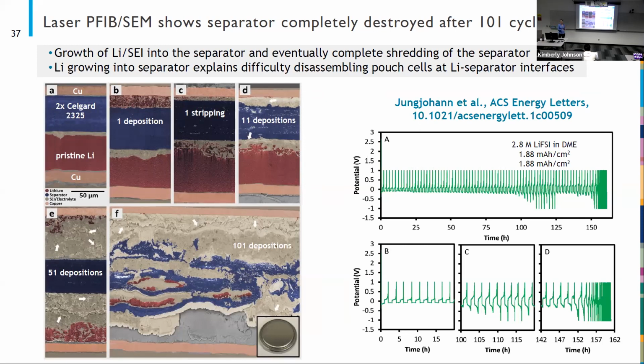And so in the first deposition, we can see we plate lithium onto the working electrode, we strip it from the counter electrode, we see lots of evidence of bulk lithium along with some SEI regions. And then we strip that away and there's a bunch of material left, right? We don't get it all back. Some of it turns to SEI and we can still see some bulk lithium there that must be disconnected or dead lithium. After 1 and 11 depositions, we actually start to see some evidence of junk forming in the separator that doesn't look like separator anymore, that we think is infiltrating the separator with SEI, potentially lithium deposits.